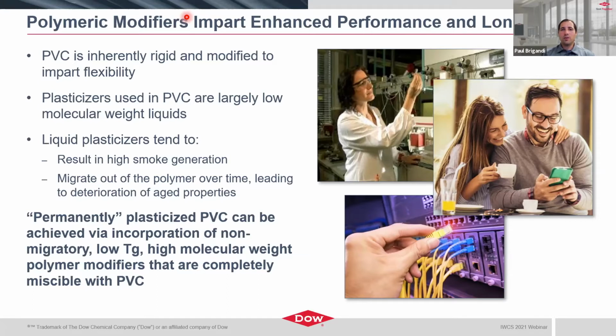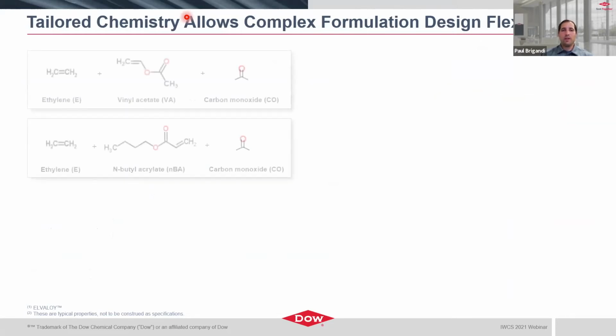So one way to address these challenges is to look at what we call permanently plasticized PVC. And that's achieved by incorporation of non-migratory, low Tg, high molecular weight polymers, which are completely miscible with the PVC so that they don't tend to migrate out over time, and really leads to the longevity and high performance that we need. So we can tailor the chemistry to allow for complex formulation design and allow for flexibility when it comes to formulating different materials for a given application.